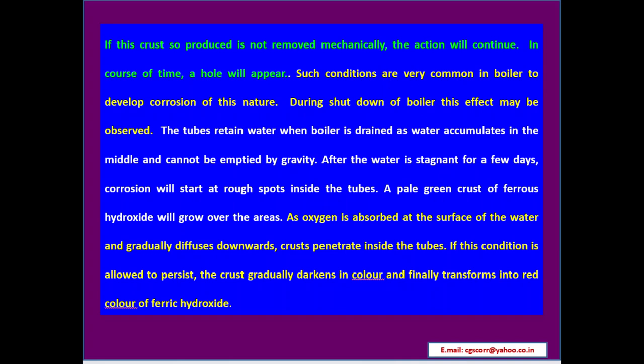During shutdown of a boiler, this effect may be observed. The tubes retain water when the boiler is drained, as water accumulates in the middle and cannot be emptied by gravity. After the water is stagnant for a few days, corrosion will start at rough spots inside the tubes. A pale green crust of ferrous hydroxide will grow over the areas. As oxygen is absorbed at the surface of the water and gradually diffuses downwards, crusts penetrate inside the tubes. If this condition is allowed to persist, the crust gradually darkens in color and finally transforms into the red color of ferric hydroxide.